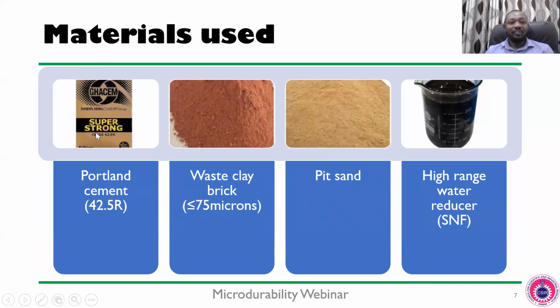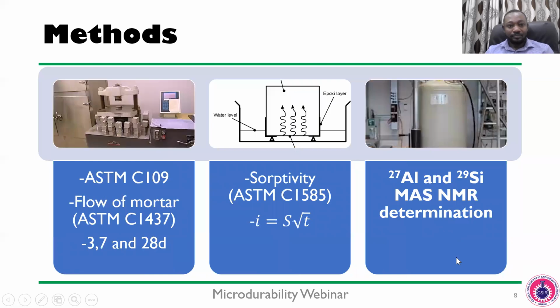So the materials that were used for the study: I have Portland cement, waste clay brick that was milled, having a size less than 75 microns, and I have pit sand. Then we have a high range water reducer in the form of sulfonated naphthalene formaldehyde. So for the method, we prepared our mortar using the ASTM C109 method, which prescribes a way of preparing mortar. And then we determined the flow of the mortar using ASTM C1437. These mortars were cured for 3, 7, and 28 days in lime saturated water solution. For the sorptivity test, the method was in accordance with ASTM C1585. And then we performed the NMR using the solid state aluminum and silicon NMR method.